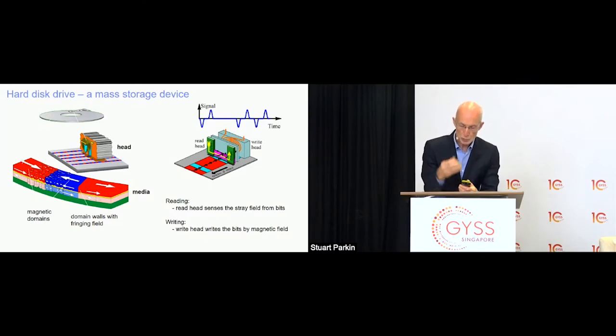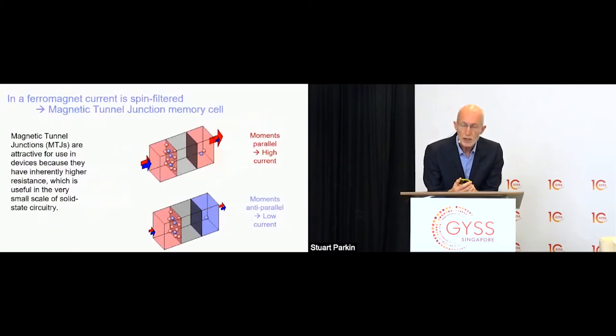So spintronics was able to build, using these concepts of long-range oscillatory coupling, interfacial spin-dependent scattering, the synthetic antiferromagnet, and the proper materials, cobalt and copper, a device that could operate at room temperature that was 10,000 times more sensitive to tiny magnetic fields than any other device, and that's still true today. So this enabled then, within just a few years, the area of these magnetic bits to be shrunk by 1,000 times, and thereby to increase the storage capacity of a magnetic disk drive by many orders of magnitude. This was the first success of spintronics.